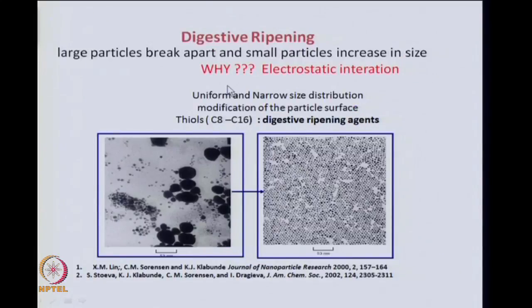The other alternative to Ostwald ripening is what is called the digestive ripening. This is not the thermodynamically driven process. This is against the thermodynamically driven process, where large particles break apart and small particles increase in size. So, this is just the opposite of Ostwald ripening. In Ostwald ripening, you have small particles getting removed from the system and the larger particles growing. In this case, large particles break apart and small particles increase in size.